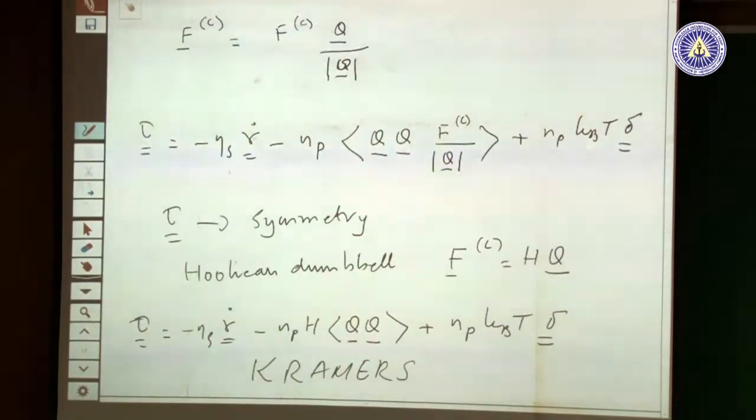Sir, this won't give us normal stress differences. The Hookean, of course it will give, you won't see it from the second term. Okay, yes, in a simple shear flow the simplest model will lead to zero normal... No, you will get the first normal stress difference non-zero, the second normal stress difference is 0. We might actually tomorrow work out this, so be patient. What I'm saying is that the prefactor NpH is constant.